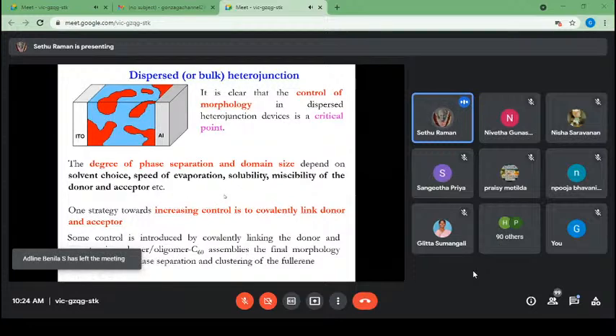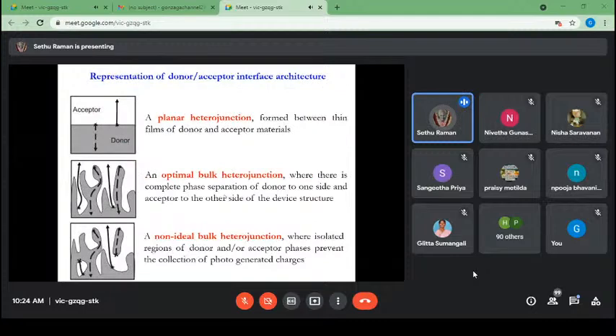One strategy towards increasing control is the covalent link between donor and acceptor. A planar heterojunction is formed between thin films of donor and acceptor material. Here you see dissociation of a charge carrier at the interface. Once a charge carrier is dissociated, it moves towards the concerned electrodes. But this is a bulk heterojunction. In an optimal bulk heterojunction there is a complete phase separation, with the donor to one side and the acceptor to the other side of the device. So excitons are easily dissociated at the interface of the domains and connected to the concerned electrode. This is our desired choice, the optimal bulk heterojunction, compared to a planar junction.